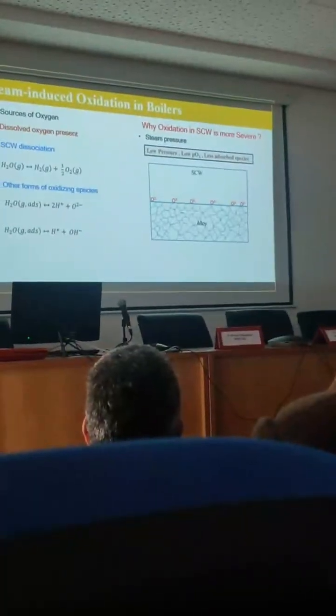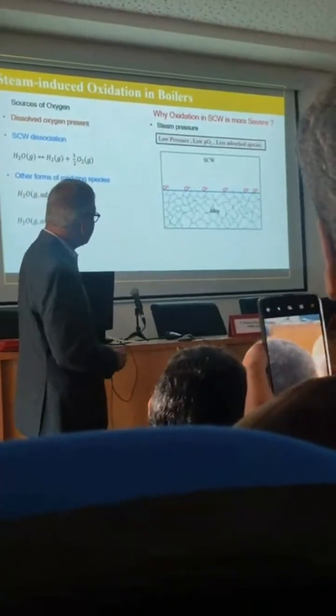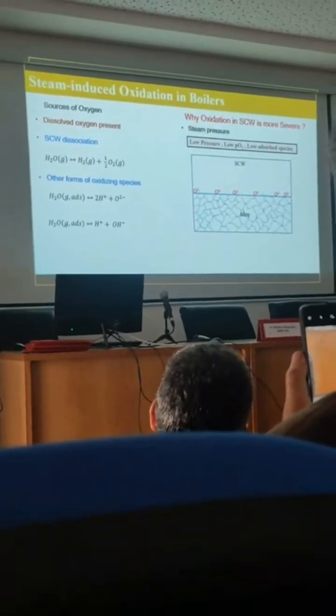So what happens? You have alloy here, you have oxygen ions sitting here, so there is going to be an oxidation. These ions will react with metal and form metal oxides. Okay? This is called supercritical water, and this is a problem that happens. Please see that there are free oxygen ions in this, and they sit on the metal surface and start oxidizing the metal surface.